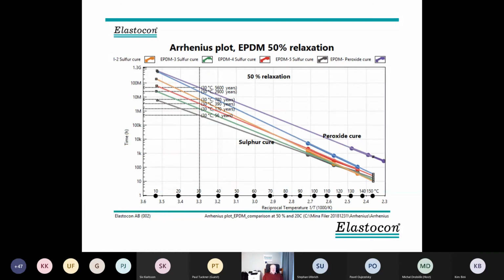We've done quite a lot in the last 3-4 years. We tested quite a lot of relaxation on sealing rings for water pipes. Sealing rings for water pipes or wastewater, not hot water. We have a lot of pipes in the ground in all cities, and they start to leak, or have done so quite a long time sometimes, because originally we had natural rubber seals and they don't last so long, and then we changed to SBR seals, and now we have EPDM seals. But there can be quite enormous spread in EPDM.